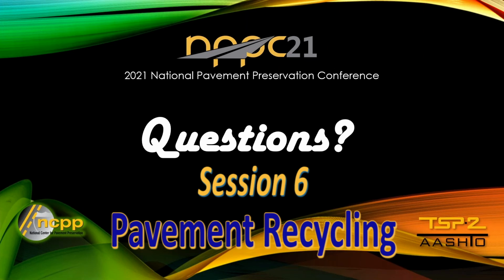Next question. What is the structural coefficient difference between HMA and CIR? I'll answer that one. It's about 80%. ARRA typically recommends you use somewhere on the range of 0.36 for a structural layer coefficient, and 0.44 is what's typically used for asphalt. There's some research out there that indicates that may be conservative, but it does seem to work quite well. Next question.